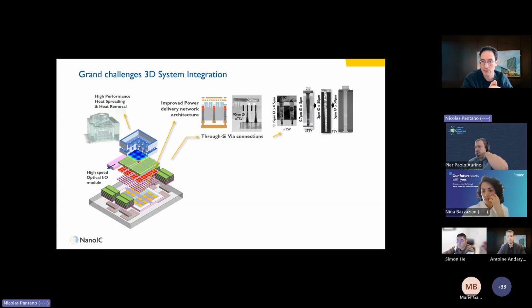And there we need through silicon via. Through silicon via, the first dimension were 10 micron in diameter for 100 micron thick. Of course, if you want to increase the density of connection, you need to scale them. That means scaling the silicon and scaling the diameter of these TSVs. And especially for this buried power rail or this backside power delivery network, the TSV needs to scale significantly in the micron scale or even below in the nanometer scale.